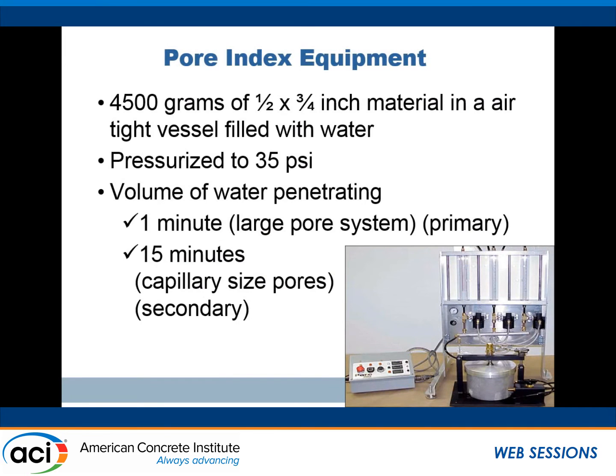Then there is the Iowa Pore Index test, which Heather alluded to a little earlier. Interesting approach. Basically, you take a sample of the aggregate and you squeeze a bunch of water into it. And you measure how much water goes in at 1 or 2 minutes and how much goes in at 15 minutes. And so you get two different numbers, what they call the primary and the secondary. The critical one is how much water goes in over a fairly long period of time at fairly high pressure.